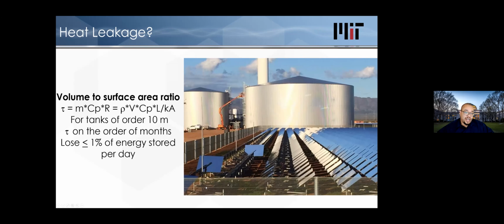The issue, though, is that the time it takes for something to cool down is actually a function of the volume to surface area ratio. So if you make something very large, the amount of volume contained inside of it is very large compared to the amount of surface area available for all this heat leakage. The heat leakage scales with the surface area. The amount of energy that you've stored scales with the volume. So as you make something bigger and bigger, what happens is the time it takes for something to cool down, which is proportional to this ratio, actually increases.